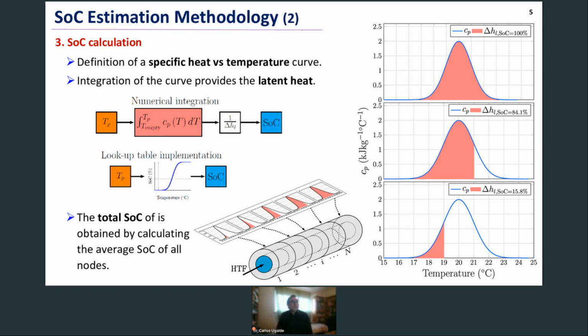To further reduce computational burden, instead of conducting a numerical integration of the specific heat against temperature curve, we define a lookup table. This is illustrated in the block diagrams. Now, we have to remember that since we have been using a discretization approach, the state of charge calculation should be conducted for each of the nodes. This is shown by the diagram at the middle of the slide, at the bottom. Therefore, the total state of charge is calculated simply by obtaining the average value for all of the nodes that have been defined.